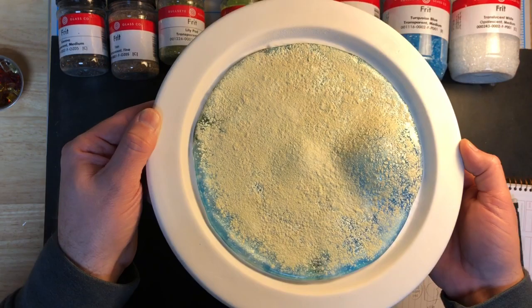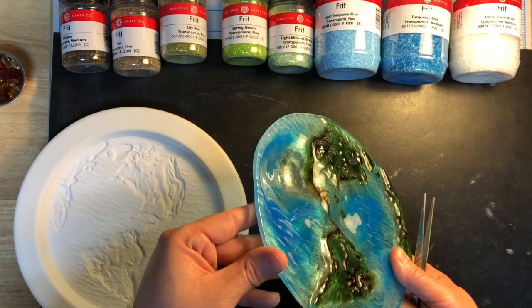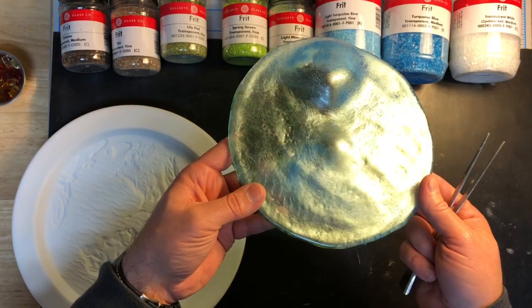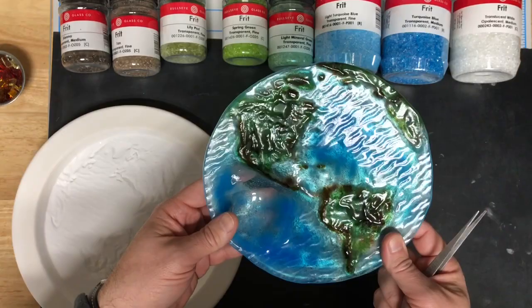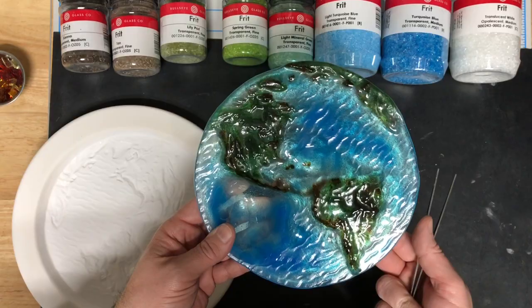I washed it up and it's really a shame that the entire Pacific Ocean here has cratered in. Can you see how big that bubble is? Because the back is really cool — the mica truly gave me a really cool effect back here. You can see all that shimmer in the light. Just awesome color, and you can see that color through this piece as well, which is what I was hoping for. In those areas around the coasts where I was complaining about the frit being lighter, that's where you see it the best. Now I've got to figure out how to fix this.